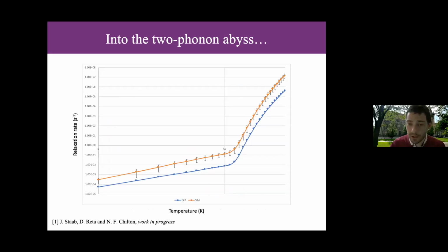And if you throw it all into the computer, and you get the Orbach and the Raman from this picture, you get a really, really nice simulation of the experiment. So orange is a calculation, fully ab initio. There's no fitting parameters there. We still have this constant line width, which I've just fixed at 10, which is sort of in the middle of the range we find experimentally. And then this blue line is the experiment.